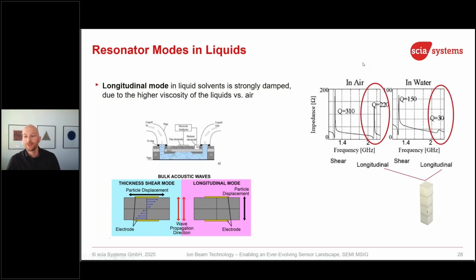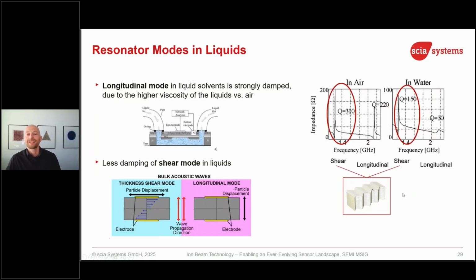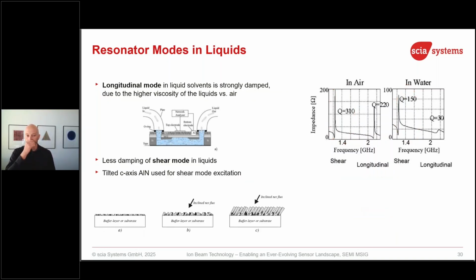Because you see, it would move basically against the water. It gets a damping. And for the shear mode, it's in plane. You don't have such a strong damping. Still some damping, but not that strong. The challenge now for us as equipment manufacturer is we have to make an aluminum nitride which is not excited in this longitudinal mode, but in the shear mode. How to do that? We need a tilted crystal axis for the aluminum nitride.